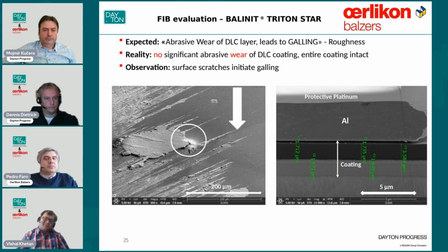But when we visualize this sticking process, it was seen that DLC coating, first of all, can resist the whole scratching process much better than steel. Point number one. Point number two, we always see that the coating is intact. It's always the surface where the sticking takes place, and hence the tool is protected. We do not damage the tool right away. One can always clean up the aluminum if the galling is heavy, or we can change the coating type. But we always see in aluminum forming and cutting that in the majority of cases, once you use a coating, the wear reduces significantly.